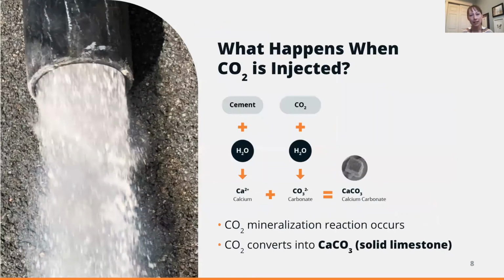Now, what happens when that CO2 is introduced into the concrete mix? A chemical reaction occurs where that CO2 finds calcium ions from the cement, and these two materials in the presence of water have almost this magnetic attraction to each other. They bind together and immediately begin to convert into calcium carbonate, which is essentially limestone. So we are turning what used to be a greenhouse gas into a mineral that now becomes permanently embedded in the concrete.